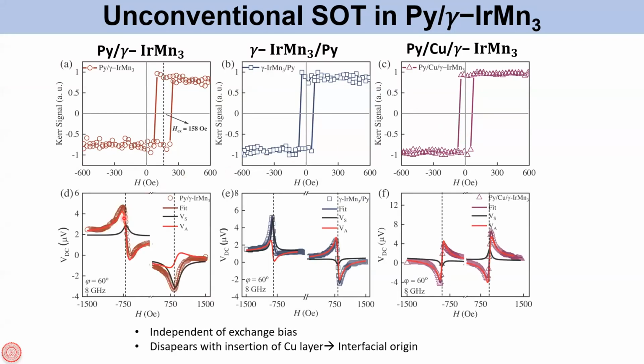So these are the STFMR results. You see that in the first case here, when the gamma IrMn3 is on top of permalloy, we see a symmetric component and an antisymmetric component. But strangely, the symmetric component shows a sign change, but also a change of magnitude when you reverse the magnetic field. So this is an indication that there is some unconventional torque present. And the same thing is happening with the antisymmetric component as well. Now, when you remove the exchange bias by reversing the stack sequence, we still see unconventional torque because you can see that the symmetric component also shows a change in magnitude as you reverse the magnetic field, which is not expected for a conventional spin orbit torque. Now, if you introduce copper between these two, then this unconventional torque more or less disappears, and now we have the standard conventional torque here.